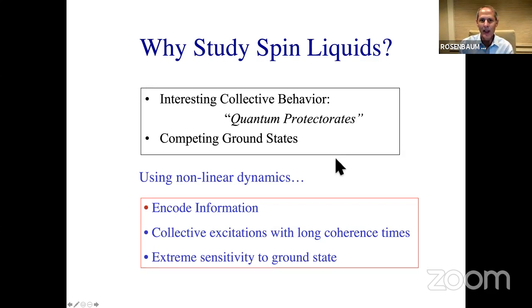The motivation for this is the comparison to this notion of only being able to solve the problem the system wants to solve versus being able to program in the problem that you want to solve. To do that, we're using the same system, the lithium holmium yttrium tetrafluoride system, but in the limit of only a few percent of the sites being occupied by spins. This spin liquid, if you will, is very interesting because it has good collective behavior. Basically, it forms isolated spin clusters that can be labeled by frequency, and I'll show you how. And there are competing ground states, of course, which I won't talk about here, but we've done a fair amount of work on. What I'm interested in telling you about, though, is our work using nonlinear dynamics.